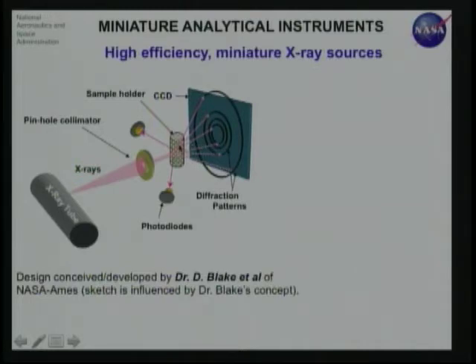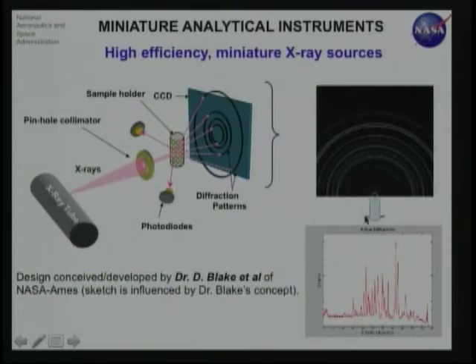The diffracted pattern is recorded on the photographic plate or CCD behind. By analyzing the pattern, you can relate it to the X-ray diffraction spectra, and then understand what the sample is. The only caveat, or one of the requirements, is that the sample must be well mixed, so you don't get statistical aberrations.